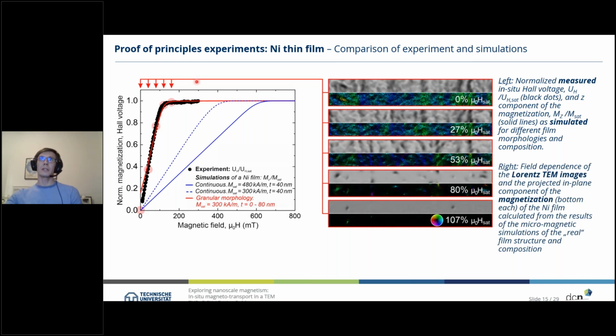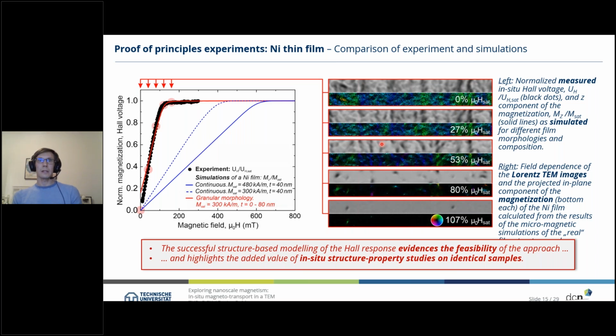And then we can use the micromagnetic simulation also to simulate now the Lorentz TEM images, and that is shown here on the right hand side, the simulated Lorentz TEM images. And this is the magnetic configuration, so the out of plane magnetization color coded, and the in plane magnetization color coded. And this shows that the speckle pattern which we have seen in the Lorentz TEM images is nicely reproduced here by this granular morphology, and starts then to vanish when we go towards saturation of the thin nickel film. So this very successfully showed that using the combination of Hall measurements and Lorentz TEM gives new insights into the structure property relations of magnetic materials.